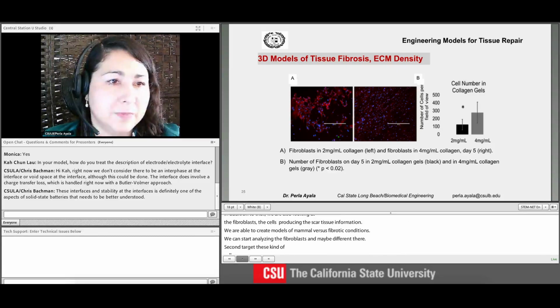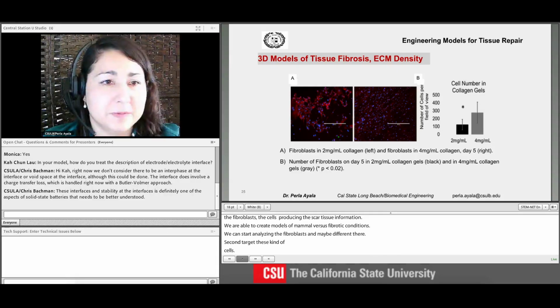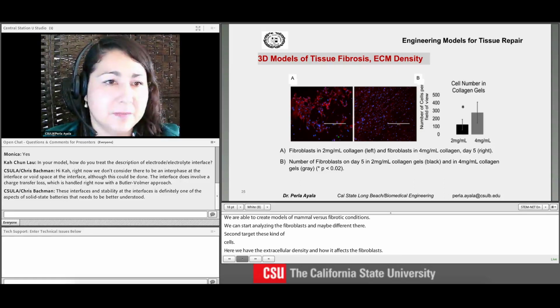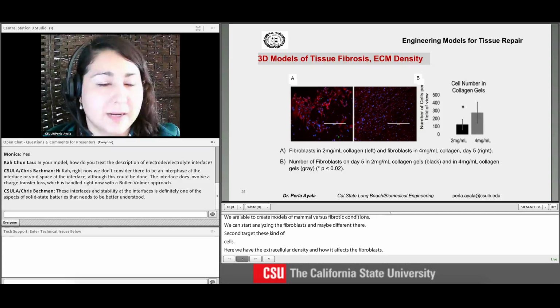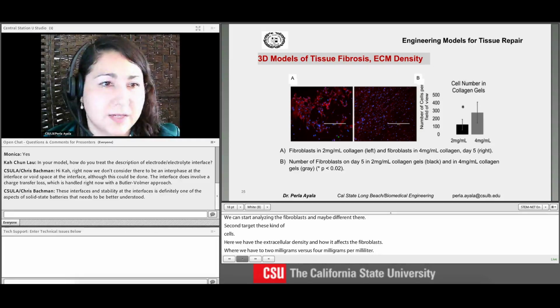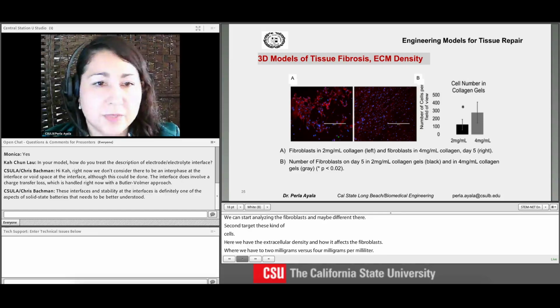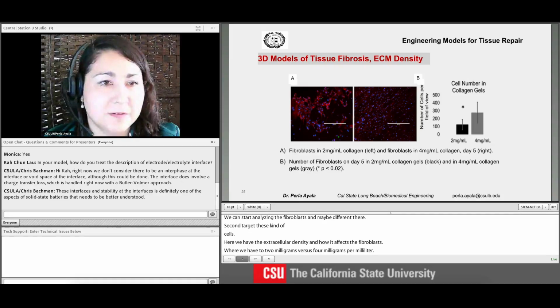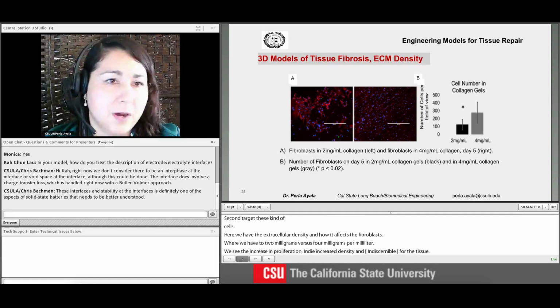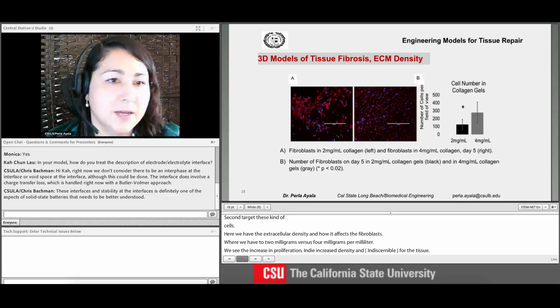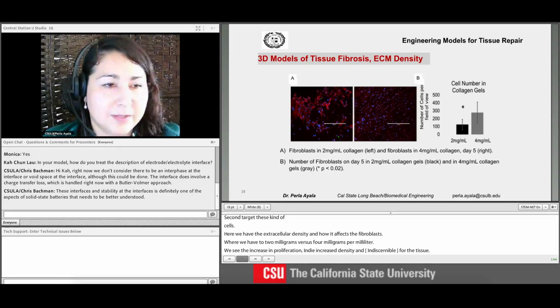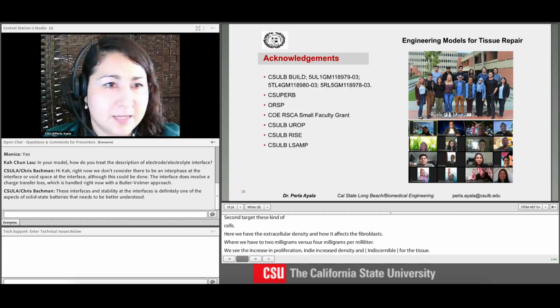So here we have 2 milligrams versus 4 milligrams per mil, and we see an increase in proliferation once we have this increased density, which also results in higher stiffness for the tissue. And so we're looking at these two concepts of implantable scaffolds, models for fibrotic conditions, and we're looking forward to continue to expand on this.